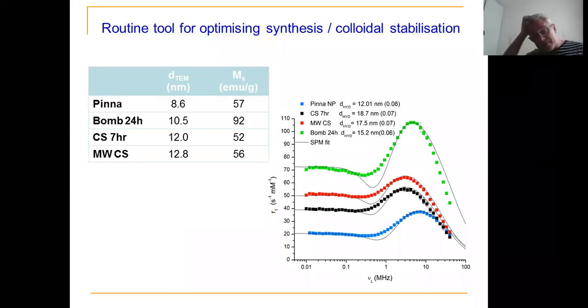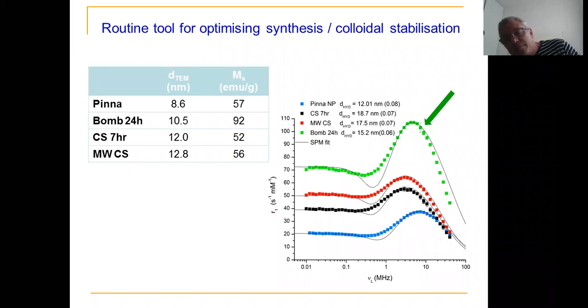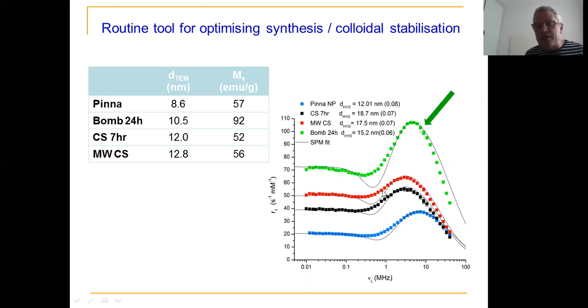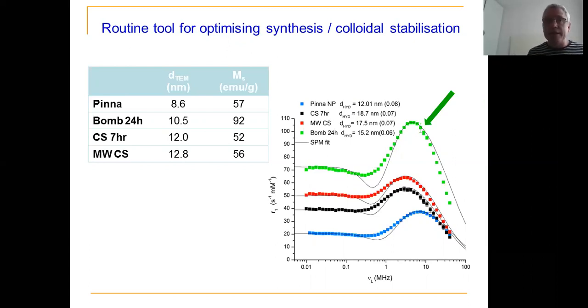More routinely in the lab, we use this method to characterize our particles made for MRI, hyperthermia, and other applications. We can extract relaxation profiles that tell us something about each sample. Typically we see curves similar to a black curve for 10 to 12-nanometer nanoparticle suspensions, from which we can extract saturation magnetizations. More realistically, we can determine whether a new suspension is magnetically similar to one made the previous week, and then use that material for a given application.